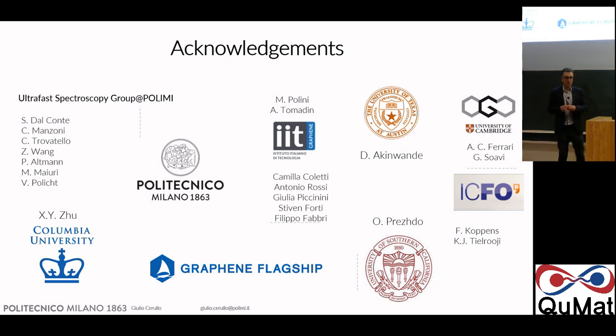So what you measure with this decay is essentially the electronic dephasing of the transition that comes out if you make a fit. It's on the order of 30 femtoseconds, which is what you expect for the electronic dephasing of this excitonic transition at room temperature. So this is the reason why this valley polarization decays. But if you drag it, you bring it every time back to the original state, or not? Well, the point is that you have a delay between the two perpendicularly polarized pulses. When this delay is much longer than the electronic dephasing, you cannot do this anymore, because you cannot get this coherent valley polarization.